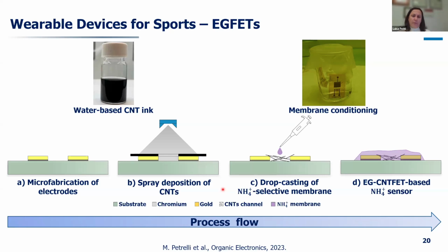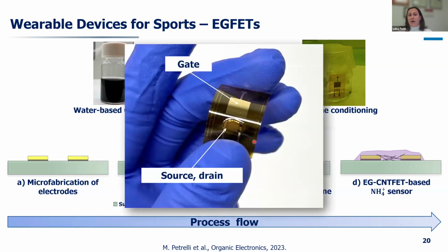This is the fabrication, so it's not fully printed, because we are evaporating the chromium gold electrodes on polyimide, so on plastic substrates, and we're doing a lithography and lift-off process. Then we are printing, so we're spray depositing the carbon nanotubes. We're drop casting the membrane, and then we're doing a membrane conditioning. That's very important to stabilize the sensors. And this is how it looks like.